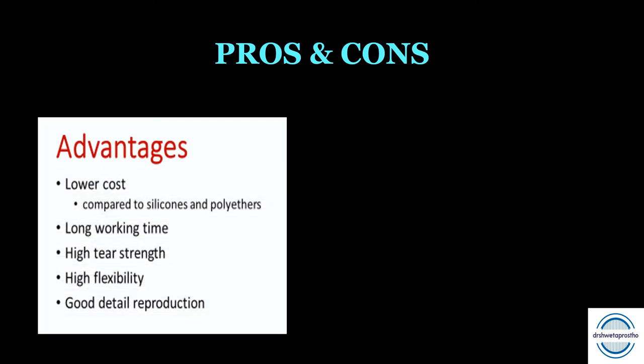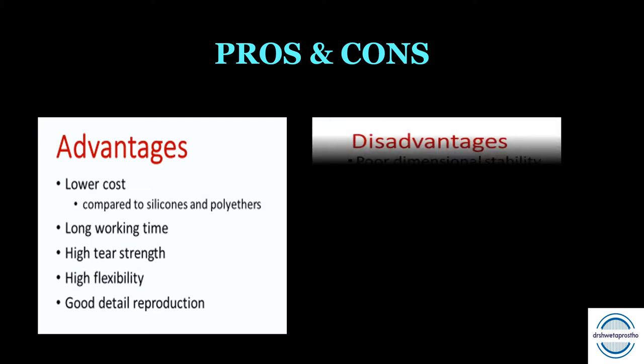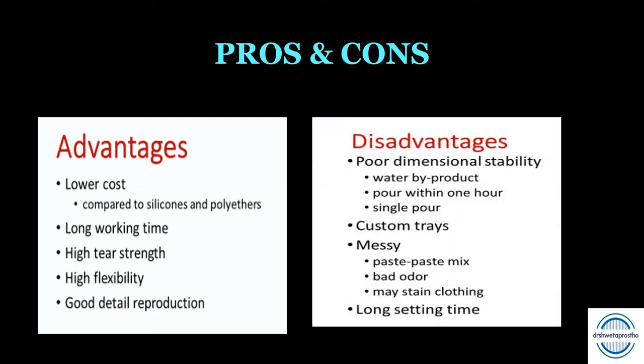Advantages of polysulfide: lower cost compared to silicones and polyethers; long working time of 4–5 minutes; high tear strength of around 4000 g/cm²; high flexibility; excellent detail reproduction; and good shelf life of around two years.